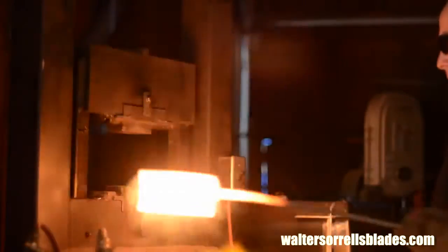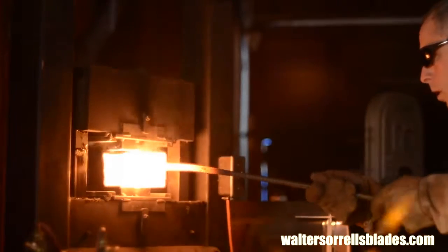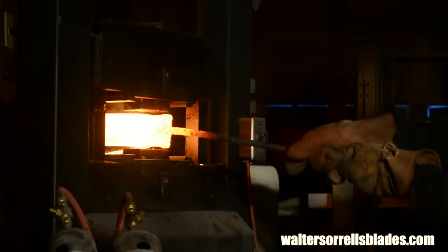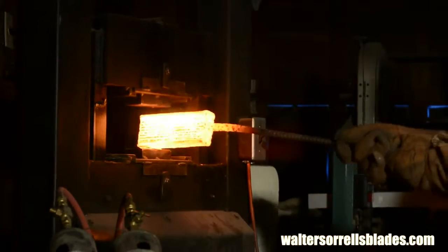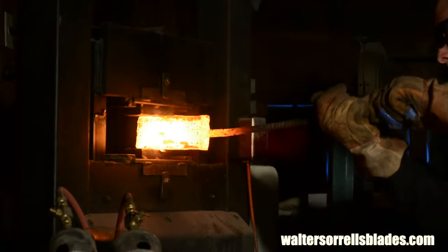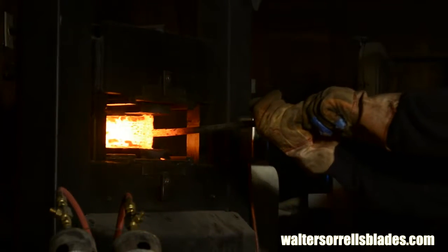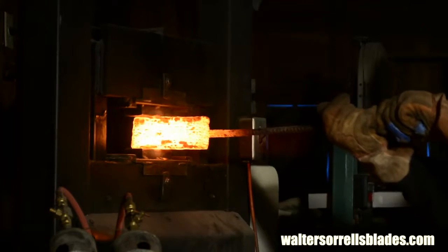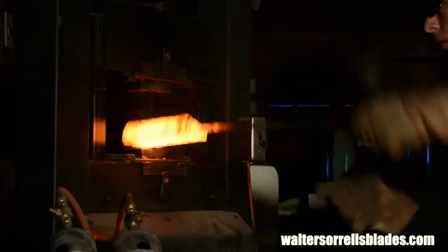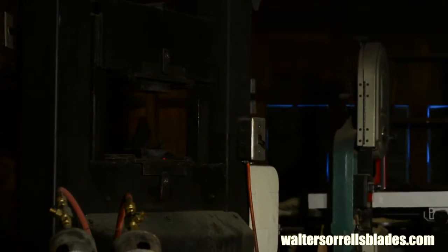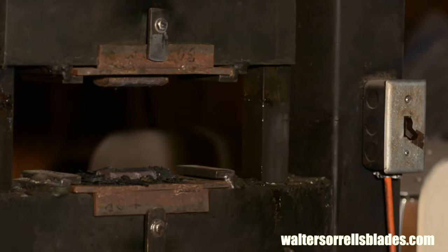Once the billet's screaming hot and the borax is boiling energetically, I'll pull out the billet and press it very gently and very quickly in the press, making sure that every section of the billet gets enough pressure to set the weld. Some people prefer to set the weld with their hammer, rapidly tapping all the way around the billet. That works fine, but I don't have any problem getting good welds in the press.